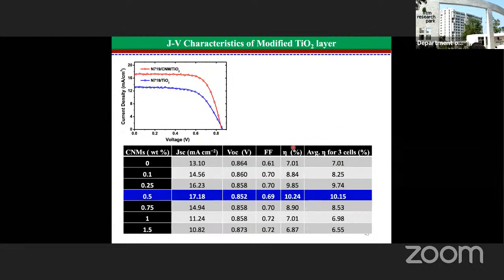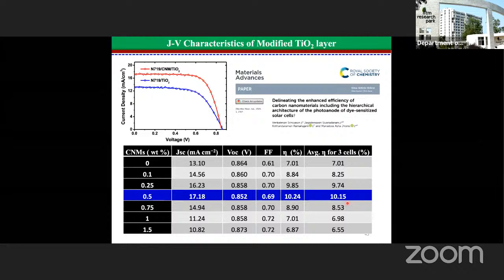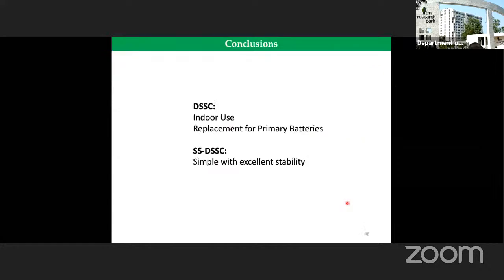That's what happened. This is N719 dye, a commercial dye, with and without the CNM. We could see there is an improvement when you simply add 0.5%. Too much and it doesn't work. Just 0.5% she added, and the performance jumps from something like 7%, which is for this commercial dye, to 10%. So same dye, same TiO2, just a small amount of 0.5% of CNM she added, a magic. I think she published this as a corresponding author, and I like the way it came out.